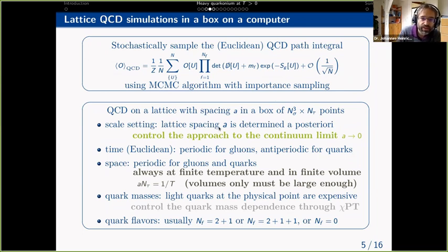We have the finite lattice spacing giving us the UV cutoff. In principle, we have to take both the zero lattice spacing and infinite volume limit in order to get real physics out of it. But as long as these effects are small enough, we can live with whatever we get. So we have periodic boundary conditions for gluons in time and in space, anti-periodic for quarks in time and periodic in space. And these periodic boundary conditions in time imply that all of the simulations that we do are essentially at finite temperature, and the temperature is the inverse of the temporal extent of the lattice, so a, the lattice spacing, times N_T, the number of points in time.